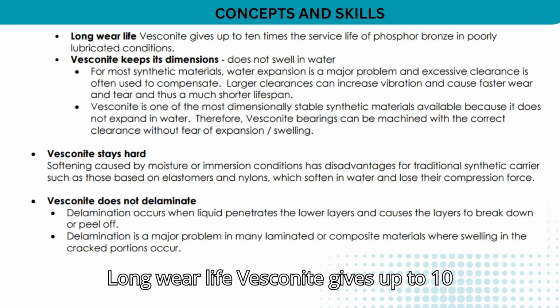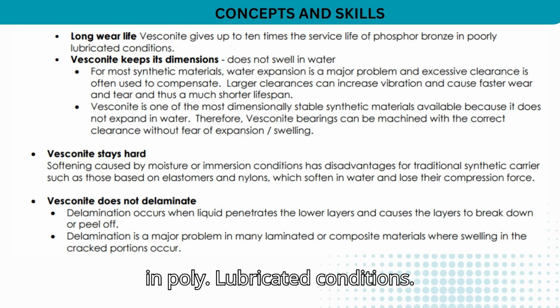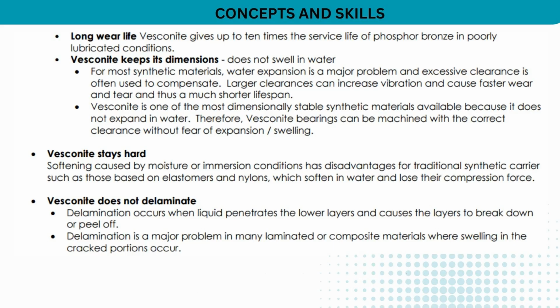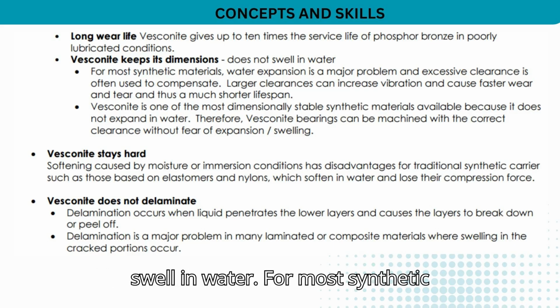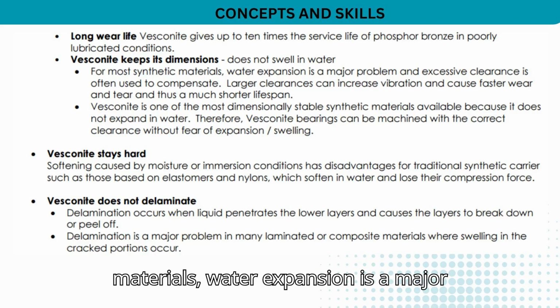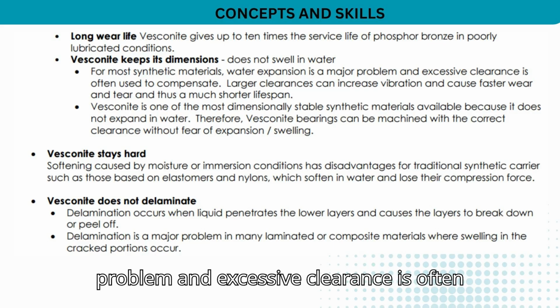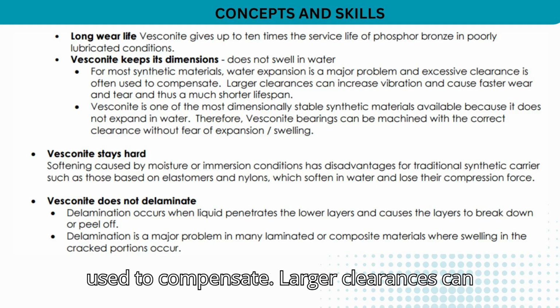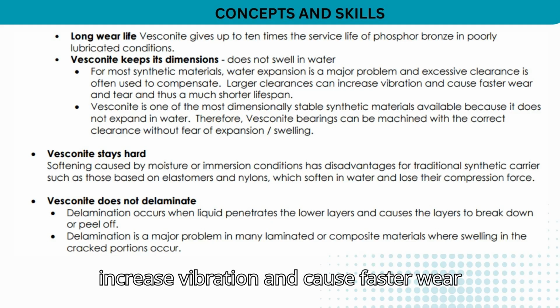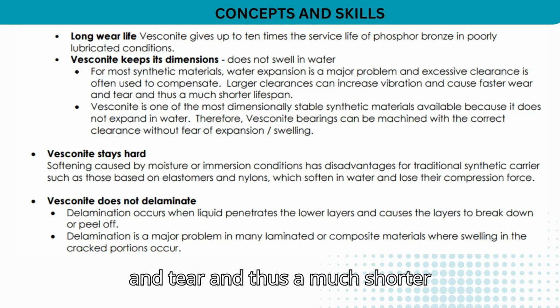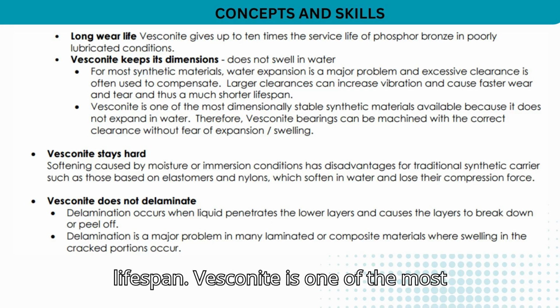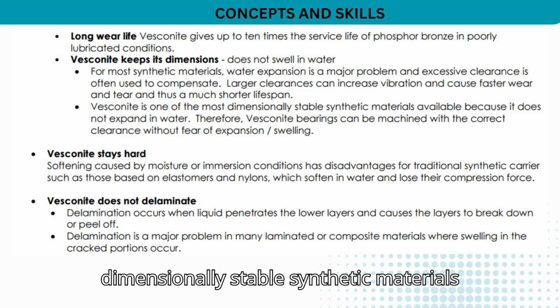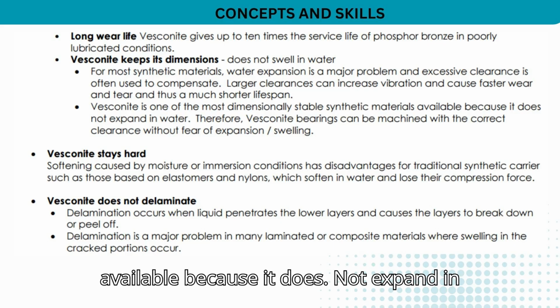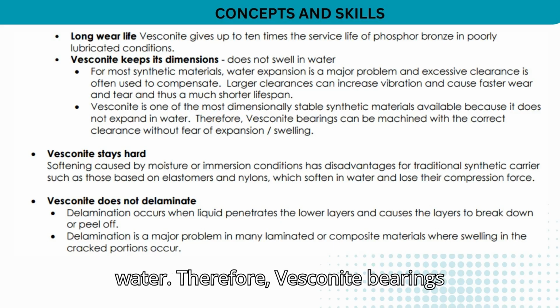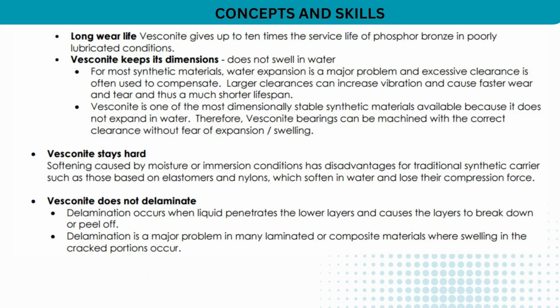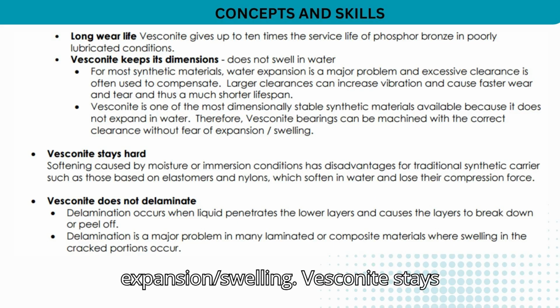Long wear life. Vesconite gives up to 10 times the service life of phosphor bronze in poorly lubricated conditions. Vesconite keeps its dimensions, does not swell in water. For most synthetic materials, water expansion is a major problem and excessive clearance is often used to compensate. Larger clearances can increase vibration and cause faster wear and tear and thus a much shorter lifespan. Vesconite is one of the most dimensionally stable synthetic materials available because it does not expand in water. Therefore, Vesconite bearings can be machined with the correct clearance without fear of expansion/swelling.